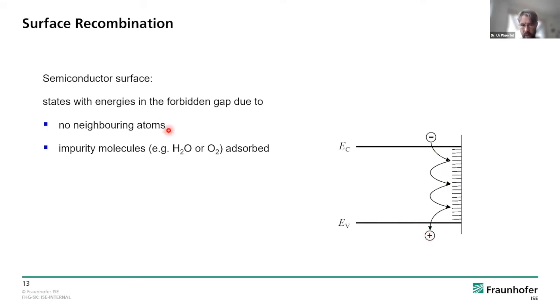So you don't have any neighboring atoms at the surface, and also many times you have some impurity molecules which are either physisorbed or chemisorbed at the surface, and they create these additional states within the band gap. Somewhere we have, however, to put a metal, right? If we want to collect our current, we sooner or later have contact with a metal because we need high conductivity.